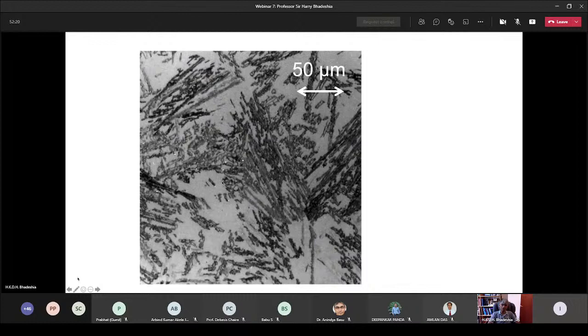Okay. Now, it's very good to have austenite films between the plates, but these very large regions of austenite, as soon as you apply a stress, they decompose into high carbon, untempered martensite. And look at the size of these regions. There's about 50 micrometers. So that's like designing a beautiful structure and then throwing a brick into it, which is 50 micrometers in size. And this is the reason why it is extremely brittle.